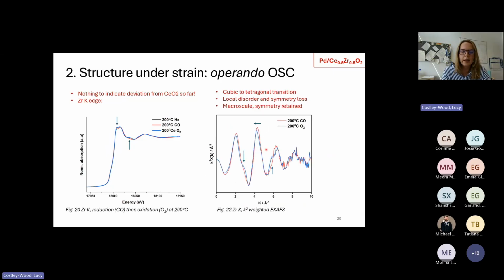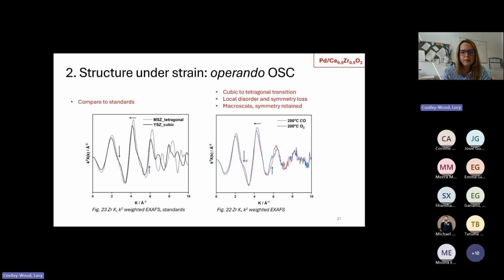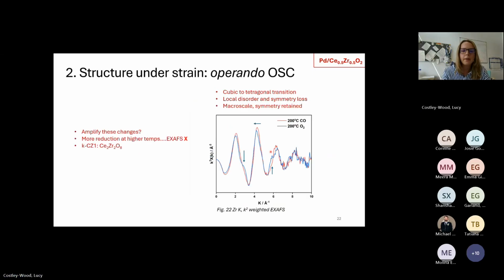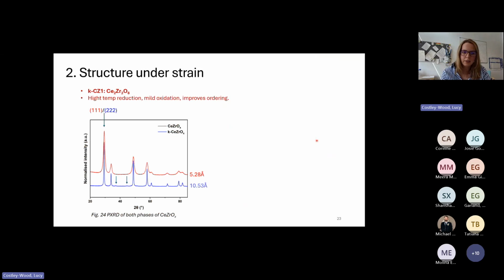We can see this also in the K space. If we compare to standards, we see this cubic to tetragonal transition here. But these changes are quite small, and if we want to really dig into what's happening to the structure, we need to see if we can amplify them. So if we increase the temperature, we'll remove more oxygen from the material, but our EXAFS will become significantly worse. So we move to the kappa phase material.